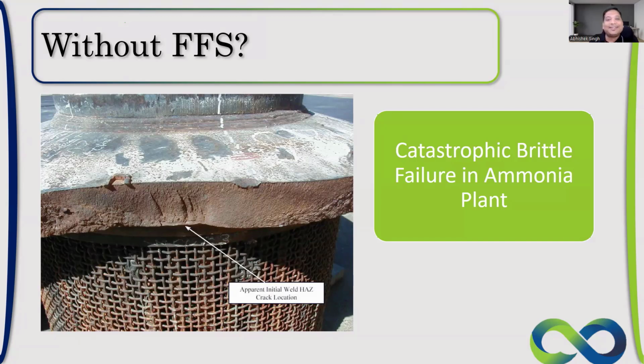And post weld treatment was not done, considering it's a small weld and not a pressure part, so how does it matter? And because of that, it's casting. Casting has a little bit higher carbon percentage, so they are prone to crack more than your normal pressure vessel material, carbon steel plate, if I take. So a small crack was found, and what was the reason for the crack?